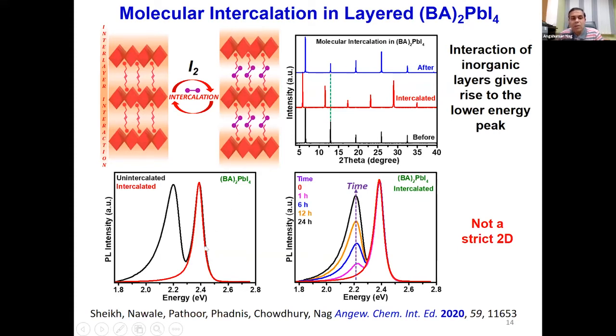And interestingly, with this intercalation, you see the black spectrum, that is before intercalation, we see the 2 peaks that we have discussed so far. But after intercalation with iodine, the low energy peak vanishes, there is some tail, but it is significantly gone, and you see a sort of single emission after intercalation. So this suggests that probably there is some interaction between the inorganic layers, and the iodine intercalation breaks that interaction, and this emission that is coming from the interaction of inorganic layers vanishes after intercalation.